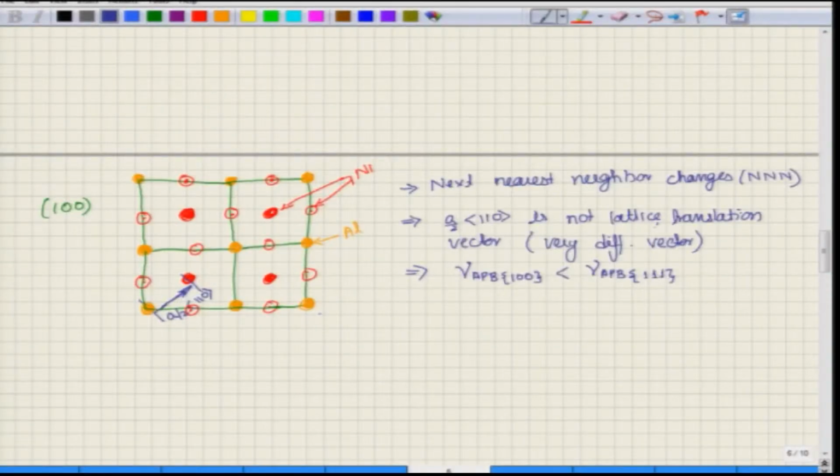Now, let us talk about what will happen if I use, instead of a/2 [110], I take a[110]. So, what happens? Now, here the orange atom is shifted all the way to the orange atom, and the red atom is shifted to the red atom. So, everything is brought back to its original position, meaning no one will be able to figure out if any changes have taken place. And therefore, we can say another thing that we can conclude from this is that